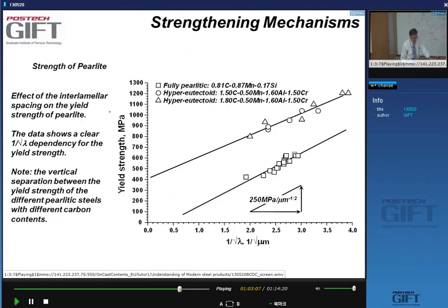The interlamellar spacing has a very pronounced effect on the strength, and in fact, you have a Hall-Petch-like relation between the strength of the pearlite and the inverse of the square root of the interlamellar spacing. And this holds for most of the pearlitic steels.